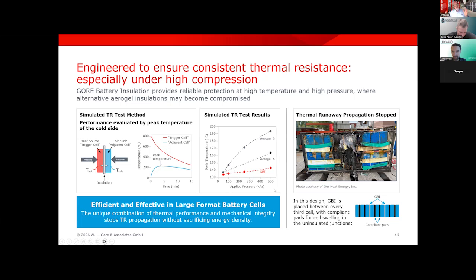So if the system starts with a thermal propagation, the pressure is increasing internally, so it's compressing the systems. And what you could see here is that if you're using an aerogel, due to the compression it's getting thinner, the temperature is rising. And this is the big benefit of this material due to the fact it's not compressible. So you have an efficient and effective tool in large format battery cells with that unique combination of thermal performance and mechanical integrity. This stops thermal runaway propagation without sacrificing energy density. So you could bring more material in because of the thickness.